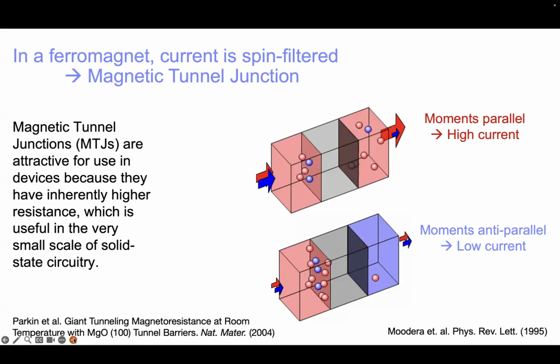And the breakthrough here was actually some materials that I published in 2004, in which we showed that you could build a structure in which the tunnel barrier itself, even though it's non-magnetic, acts like a spin filter. And the reason is that if you combine magnetic materials in which the spin up and spin down electronic states at the Fermi energy have distinct character, let's say one set of electrons is S-wave-like, and therefore the wave functions are extended, and the opposite polarized electrons are more D-like and more localized, and therefore the wave functions are less extended.